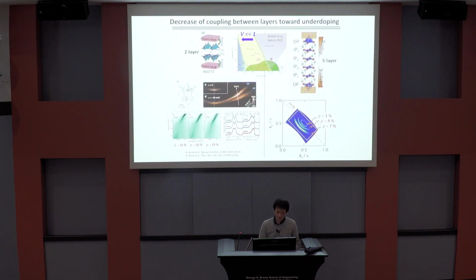And you might wonder, can each layer really be so separated, because Bismuth-2212 clearly shows bilayer splitting? But this author found that this splitting becomes less and less toward underdoping, and even at 10% doping the splitting becomes very small. But our case has much less doping, like 1 or 4%. So this bilayer coupling can be much less, so each layer can be almost isolated.